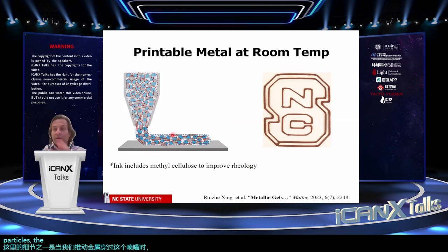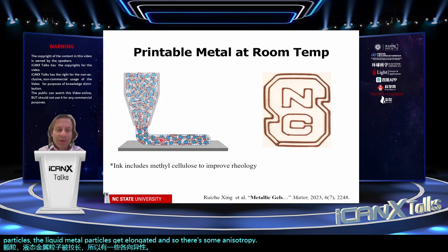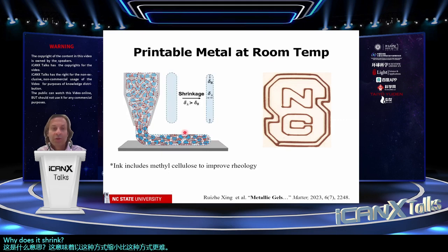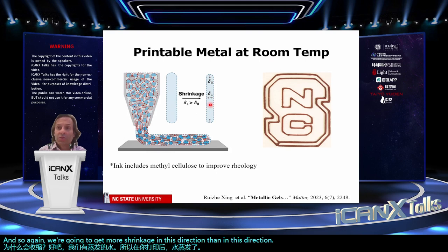Now, one of the details here is as we push the metal through this nozzle, the liquid metal particles get elongated. And so there's some anisotropy. What does that mean? That means it's more difficult for it to shrink this way than this way. Why does it shrink? Well, we've got water that evaporates. So after you print it, the water evaporates. And so again, we're going to get more shrinkage in this direction than in this direction. And that allows us to control the stress.